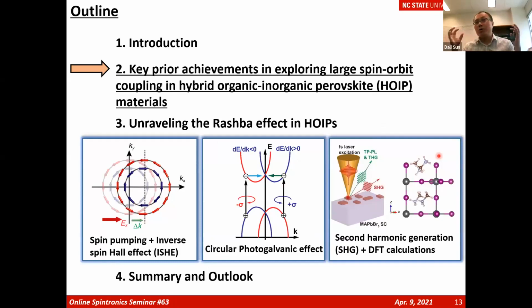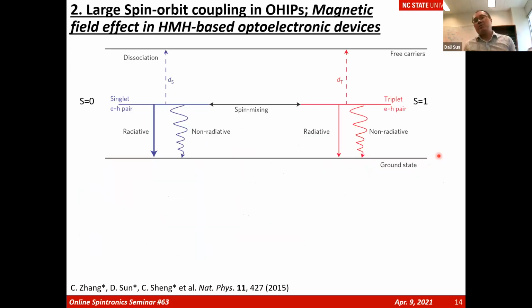Well, before we really investigate the Rashba effect, as we said, the Rashba effect needs to be formed by satisfying two criteria. One is symmetry breaking, the inversion symmetry breaking. Second, you need to have strong spin-orbit coupling. Yes, we say it contains lead, but adding the lead in such a diluted hybrid structure didn't guarantee you have a strong spin-orbit coupling. We had to study from the beginning to see whether we have such a strong spin-orbit coupling with this system before we studied the Rashba effect. Well, so that's way back to 2015.